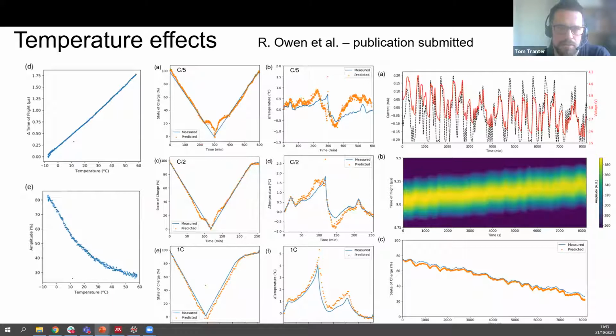the other arm of the modeling has been machine learning based. So in the lab, we cycled a cell under different temperature profiles. We cycled the cell under different cycling profiles, so at different rates: C/5, C/2, 1C. This C relates to the capacity. So 1C relates to the current that would discharge a cell completely in 1 hour. So 1 capacity, 1 hour. C/2 is half of that, so that will take 2 hours. C/5 is a fifth, that will take 5 hours. So this is the slowest one.